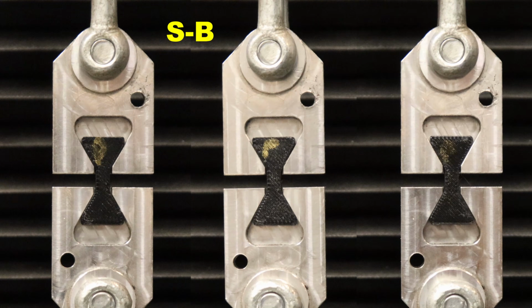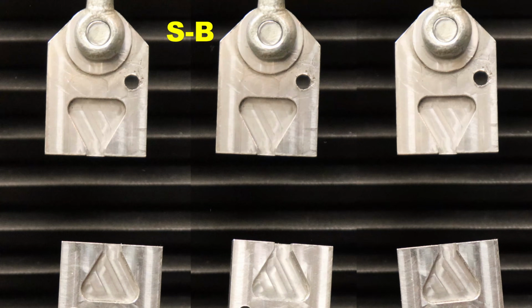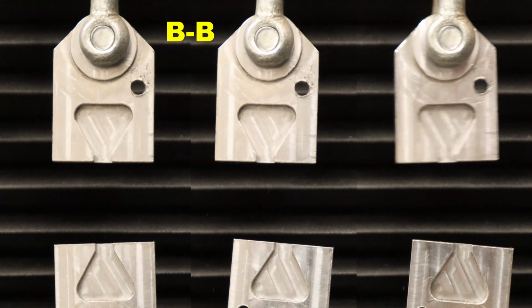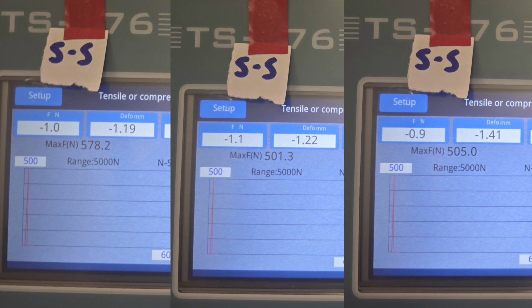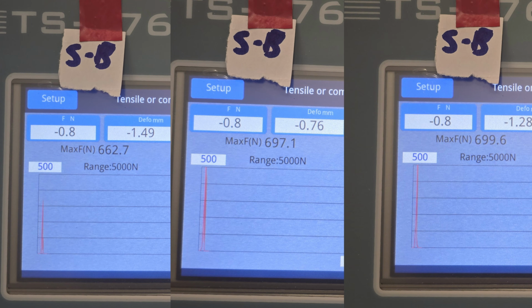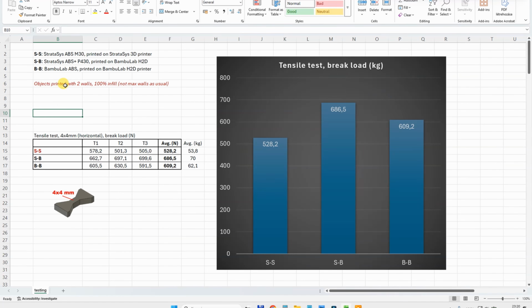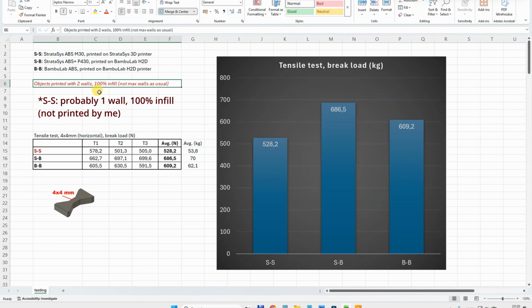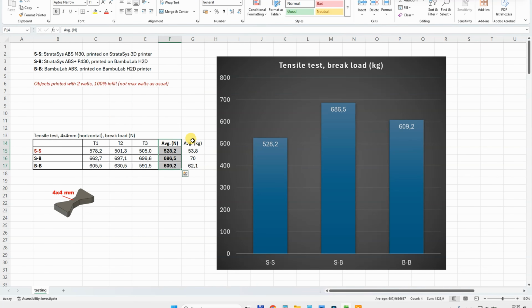Tensile test. These objects are printed in horizontal position. Maximal load in newtons, 3 measurings, but later I will show you on the graph. This is for P430 and for the Bambu Lab ABS. One more time I want to mention that these objects are printed with 2 walls and 100% infill, not maximal number of the walls as usual. And next to the newtons I also calculated the values in kilograms, because usually in earlier videos I use this unit. And if you watch the pure tensile test, the SB or P430 ABS Plus is the strongest, and M30 is the weakest. Bambu Lab somewhere between.